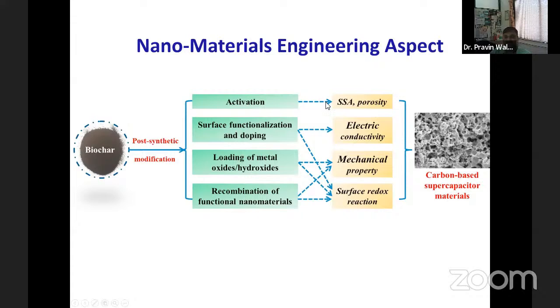And at the same time, you heat it in the presence of KOH, and you will have the activation of that particular material, and that will definitely tune the property, that is specific surface area. And more porosity will be generated inside this biochar. You see here, there is porosity generated within your carbon material, right? And the moment you introduce the porosity, the specific surface area of that material increases drastically, right?